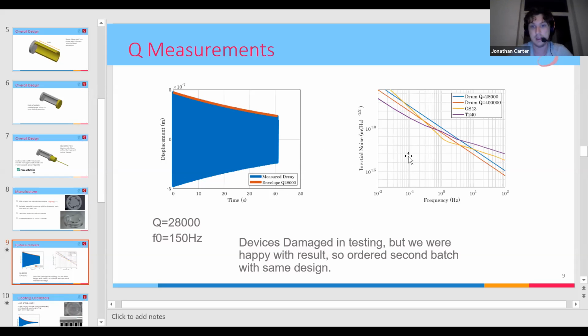On the right here, we already see the projected thermal noise performance of these inertial sensors compared with the GS13 and the Trillium T240, which are commonly used at LIGO. You can see that our noise performance is on par with both of these sensors across quite a large range of the frequency spectrum. And this is quite remarkable in a device that weighs less than 100 grams, less than 50 grams even, sorry.